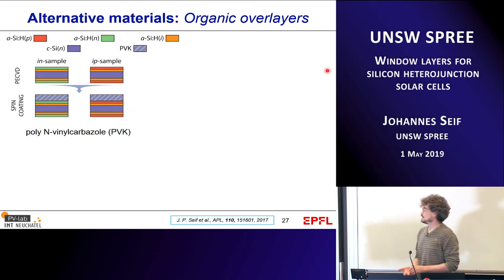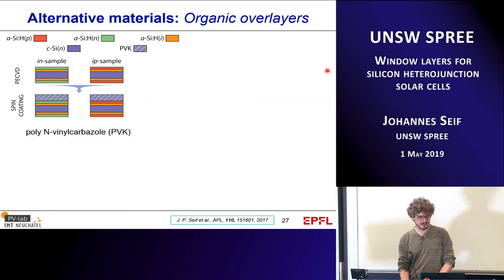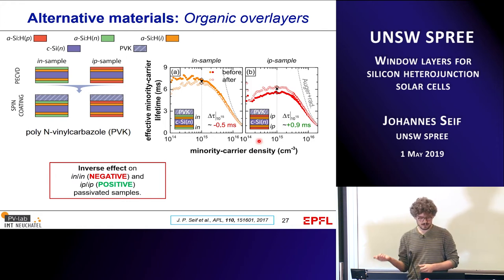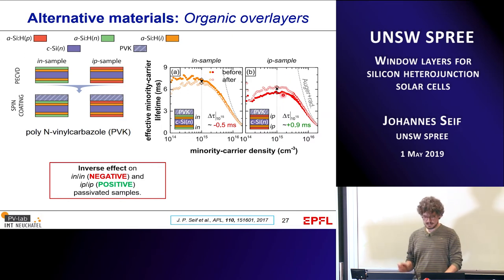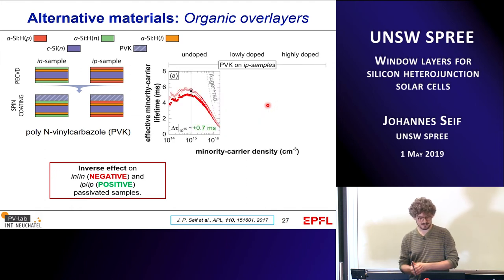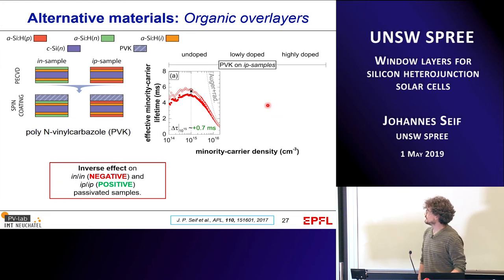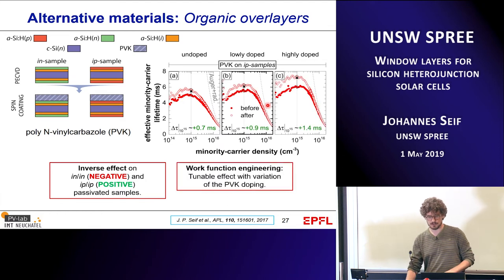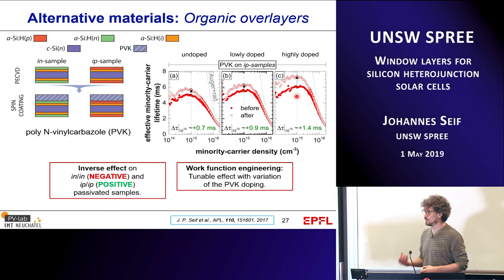We also tried organic overlayers — specifically PVK spin-coated on polished wafers passivated by either IN or IP stacks. In contrast to the zinc oxide results, we saw a decrease in lifetime for the IN samples but an increase for the IP samples. By increasing the doping of these PVK layers, we were able to amplify this effect and gain more and more in lifetime.